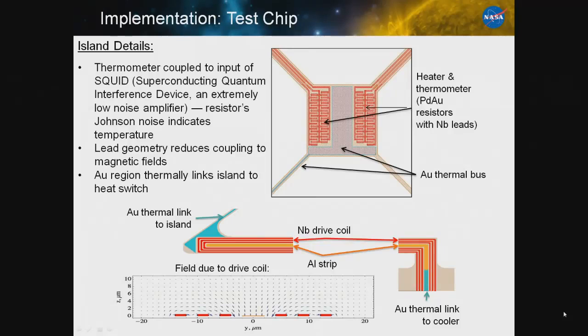The island, as I said, is linked through a thermal path, through this thermal link to our heat switch here, which is just a strip of aluminum surrounded by a niobium racetrack coil. And then by driving current through the niobium, we generate a field normal to the aluminum and can drive it normal.